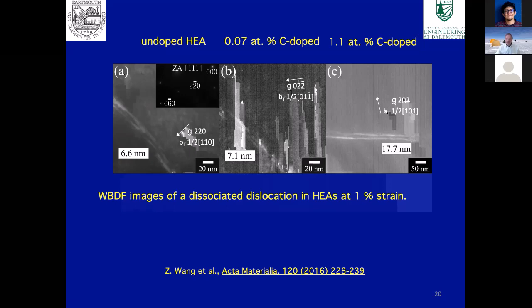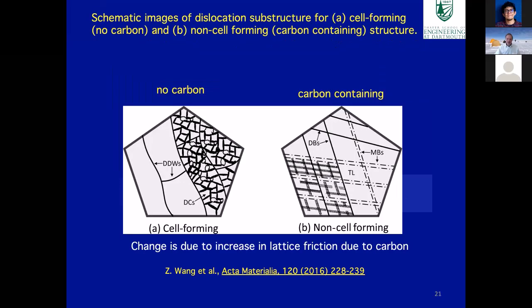So that's one of the reasons why you get this much more planar slip, is that the dislocations are confined to the slip plane. The difference between having no carbon and carbon in this material is that with no carbon, when you strain the material heavily, you get these dislocation cells, these dense dislocation walls, whereas in the carbon-containing material, you get a Taylor lattice of just randomly oriented dislocations, and these microbands which dominate the microstructure.